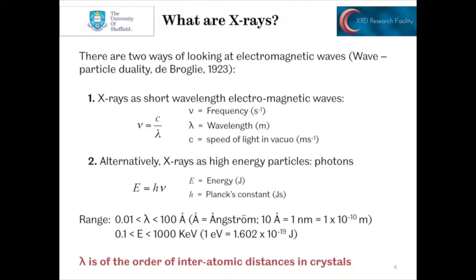The key thing about X-rays is that they have wavelengths of between 0.01 and 100 angstroms, where 10 angstroms is one nanometer. The key thing with that is that that wavelength is in the order of the distances between planes of atoms in crystals, and so the two can interact.